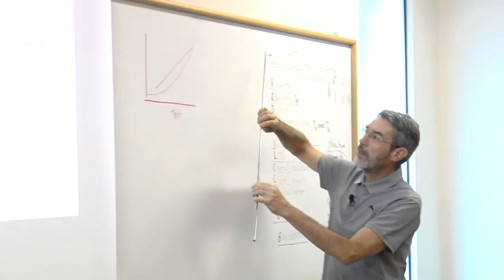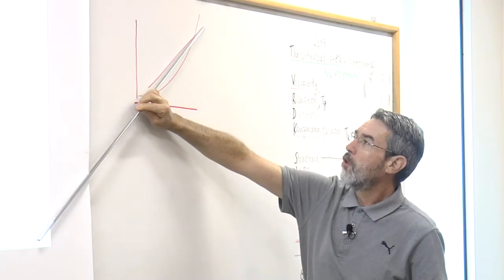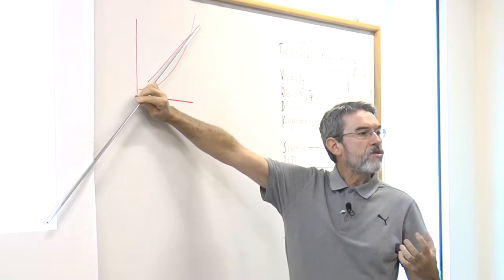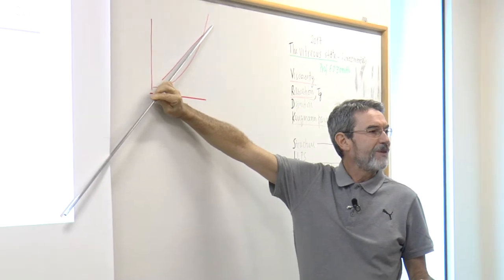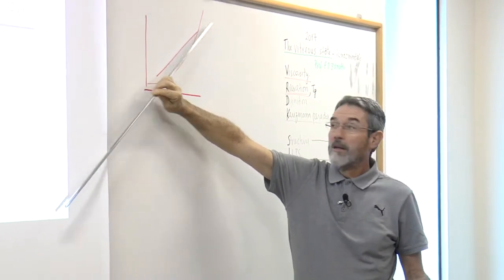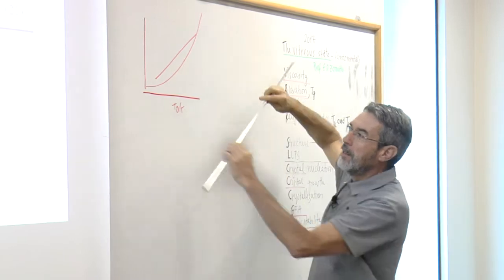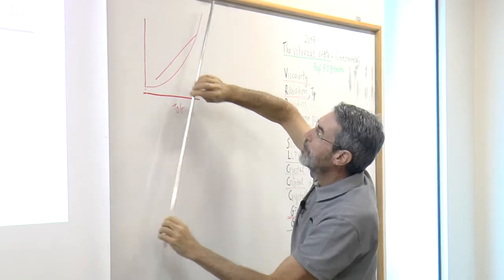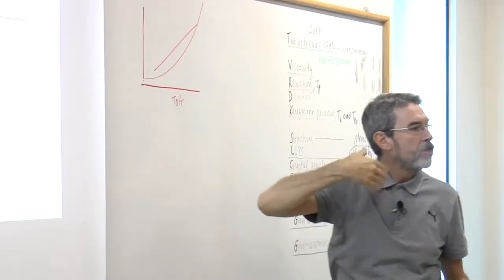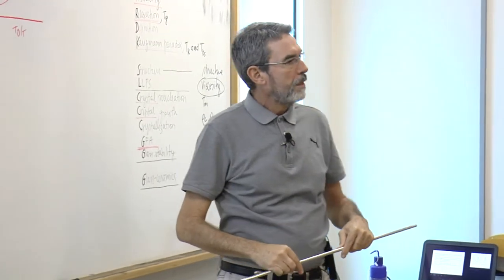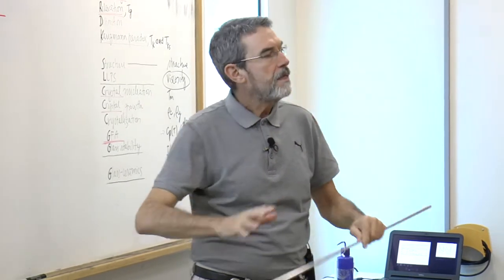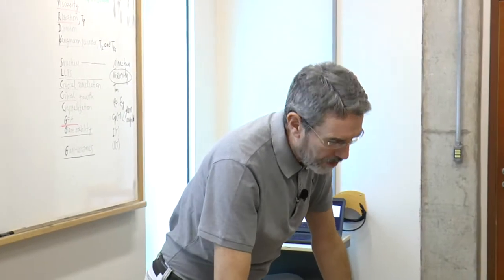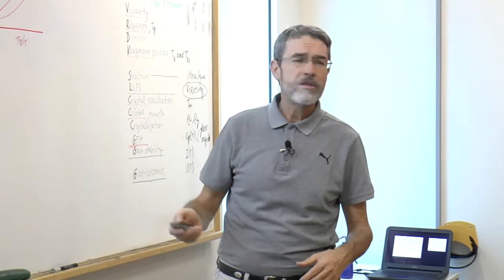The physical meaning is that for a strong liquid, the molecular structure does not change with temperature. It's Arrhenian. For a fragile liquid, see the apparent activation energy increases, increases, increases, so it changes much more with temperature. This is the easiest way of distinguishing a fragile from a strong liquid. How much the structure changes.